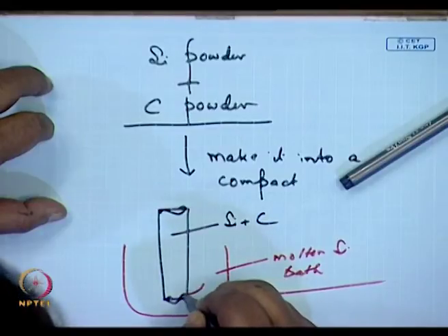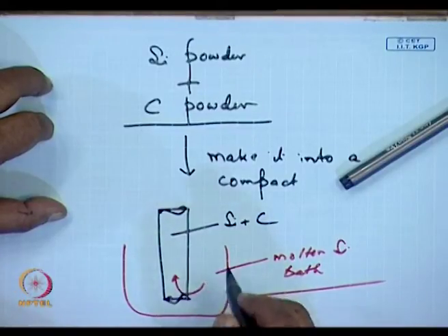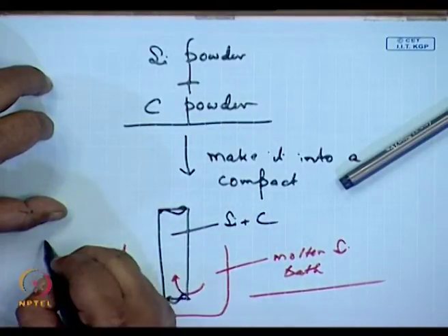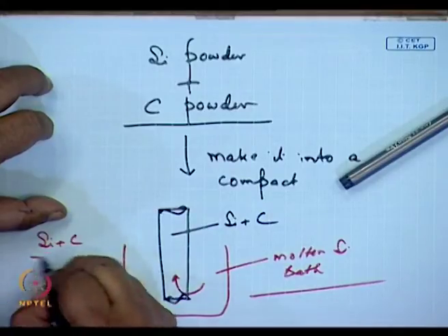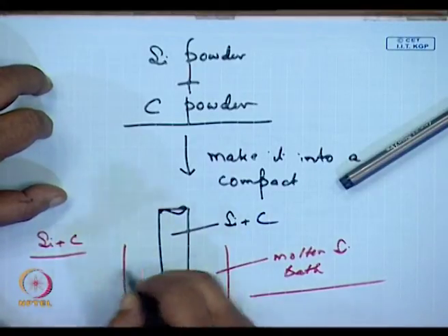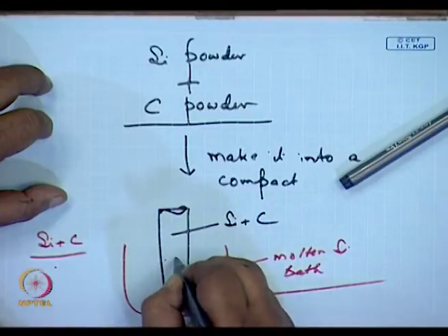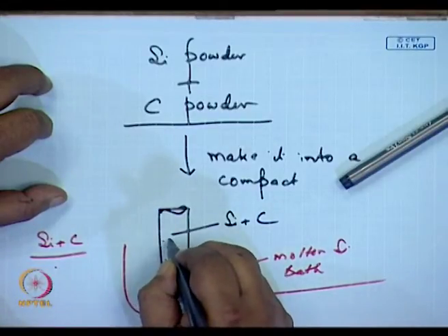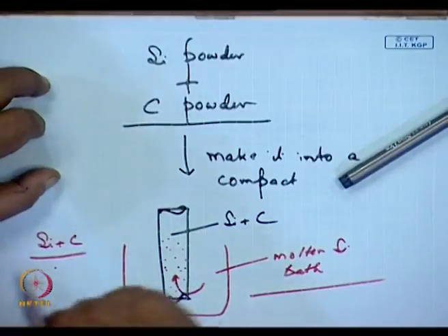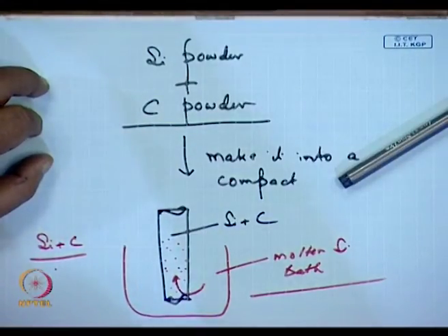The molten silicon migrates. This silicon reacts with the carbon, generating ultrafine silicon carbide, which assists in the final sintering.